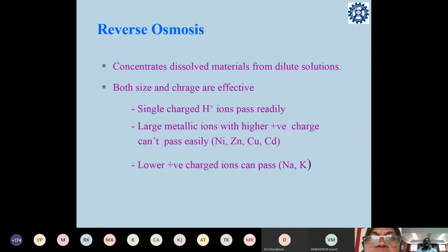If you take large metallic ions like nickel, zinc, copper, and cadmium, these larger metallic ions cannot pass easily. So that means here both charge as well as size matters. And then the third one is lower positive charge ions can pass. Like if you have salt water, it has sodium, potassium ions. So the sodium and potassium ions can pass through. But compared to protons like H+, this sodium and potassium passing through the membrane is very less. That means the singly charged proton ions can pass readily.